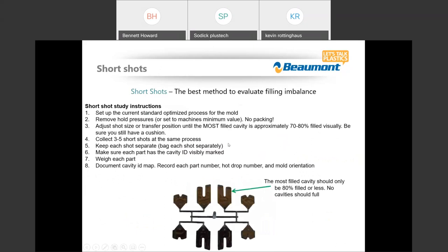So once we look at these flow groups, how do we start to identify and quantify this data? What do we do with this information once we identify flow groups? The first thing that we do with our mold is we run a short shot. And when I talk about short shots, sometimes that's a term used a little loosely in our industry. Sometimes when people talk about running a short shot, they envision a transfer position, where they're switching from first stage to second stage.